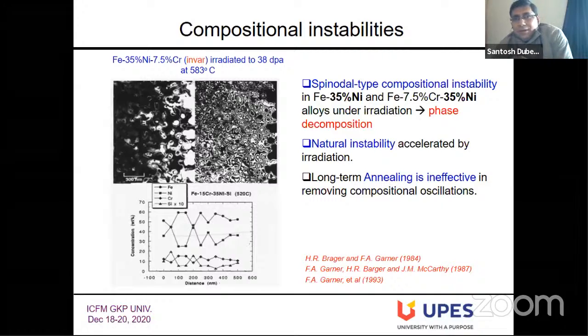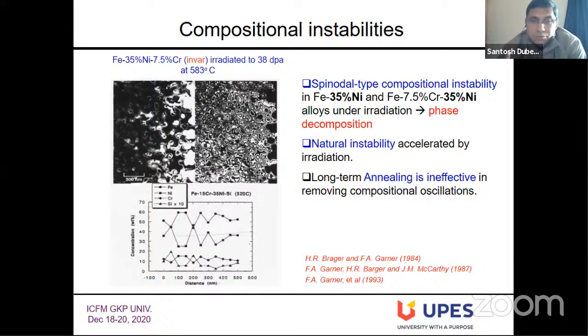You also have compositional instability. For example, say an alloy used in structures, all of a sudden you see phase separation kind of things. Spinodal type instabilities are also observed under irradiation. In such cases, even though you anneal - using an annealing process most inhomogeneities in composition can be taken care of - if there is some spinodal type instability, it can't be reversed back even though you do annealing.